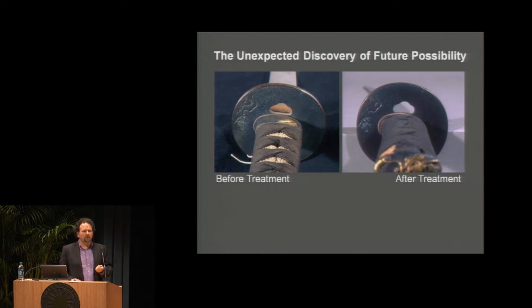However, with liquid-generated CO2 snow, I was able to greatly reduce the amount of corrosion on the surface and leave the patina intact. Even more so, leaving the patina intact, you could see where the wear from the user's hands had very gently abraded the patina away from the surface. So this was not expected. Again, this was around 2000 when I was doing this. I'd not really seen any other literature about the potential of removing corrosion from very sensitive patinas.